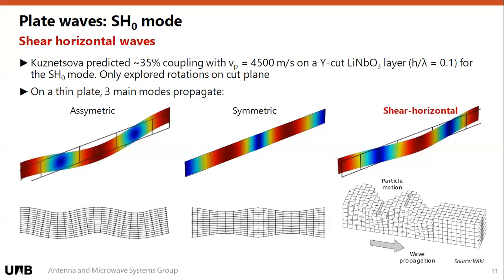Actually, it has been demonstrated, as we will show now, that if you tilt the axis further, so you don't restrict yourself to being on the cut plane, you can get even further than this, and this is what we're going to be using. So on a thin plate, this is just mechanical, not a piezoelectric plate. In any plate, you can get three main modes. There are other modes that are combinations of those, but mainly the two Lamb waves, the asymmetric and the symmetric waves, and then the shear horizontal waves.